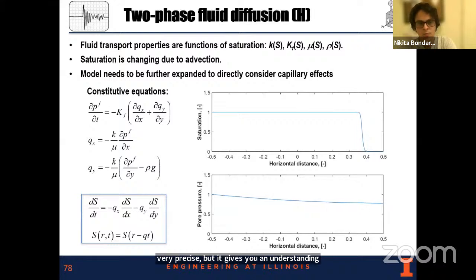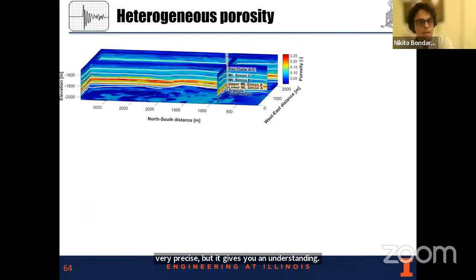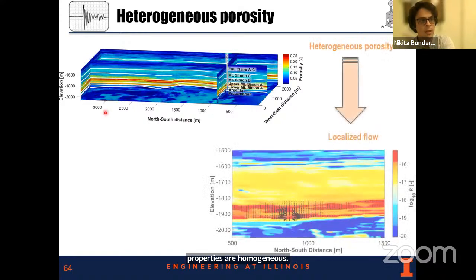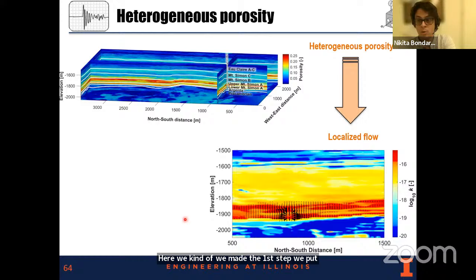But the second important thing to consider is heterogeneity, because most of this assessment is performed on relatively simple numerical domains - a layered cake structure where all the formations are flat and all the properties are homogeneous. Here we made the first step: we put in heterogeneous porosity, and after that used the porosity-permeability relationship to estimate the heterogeneous permeability. This is the permeability, and you can see because the porosity is changing, permeability is changing, and we used our lab data to calibrate it.